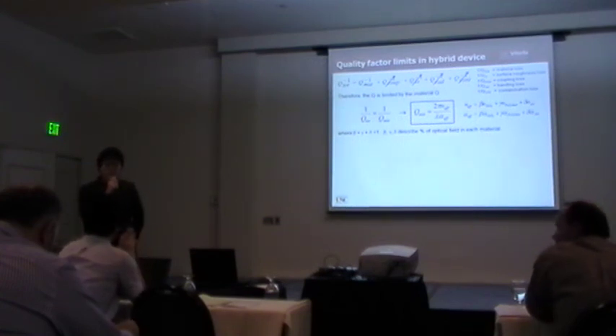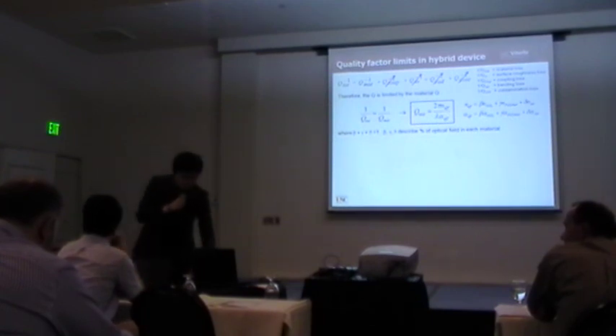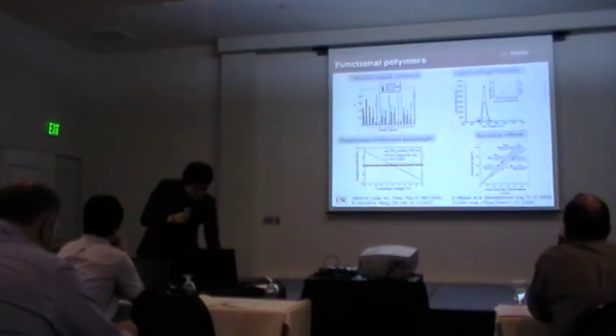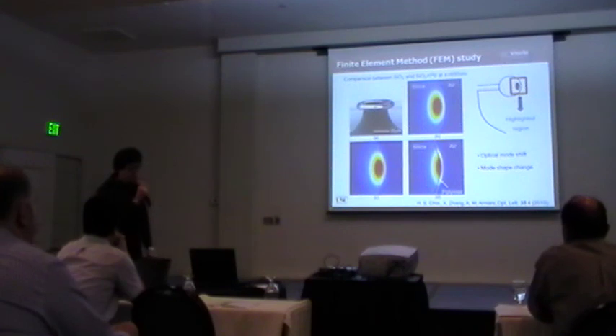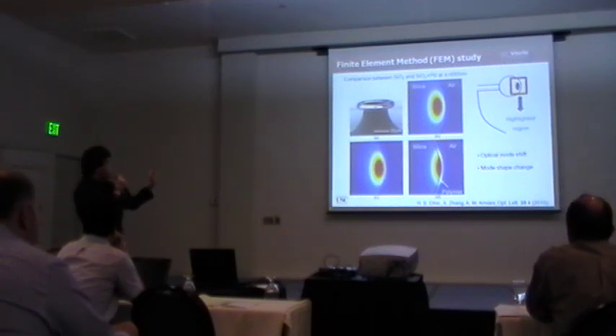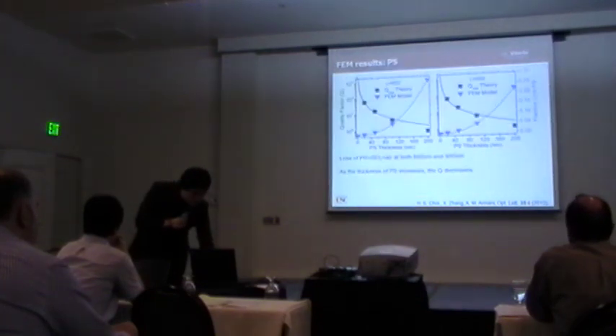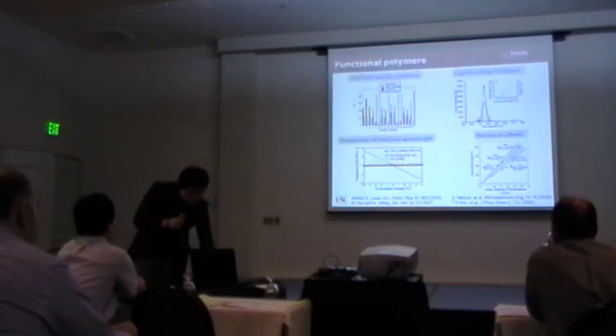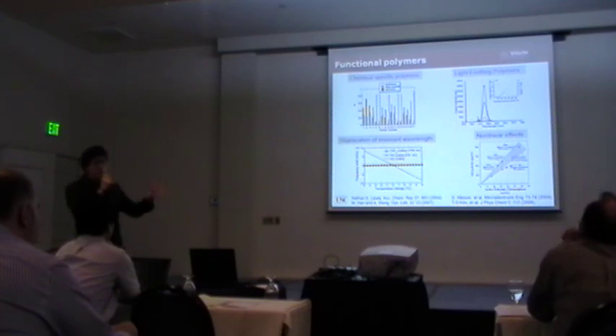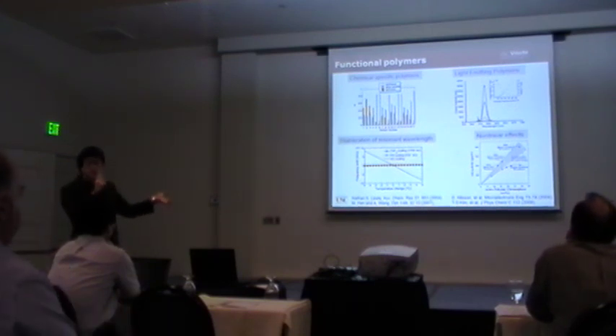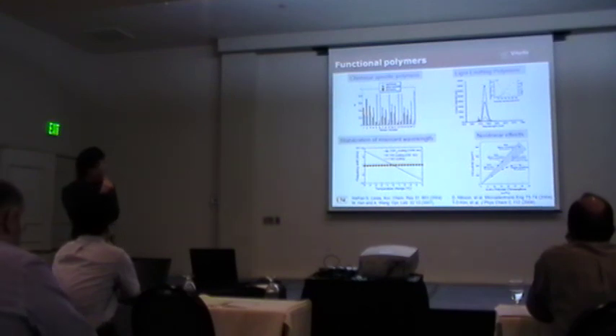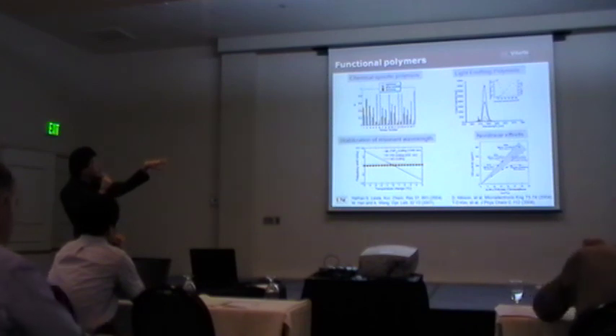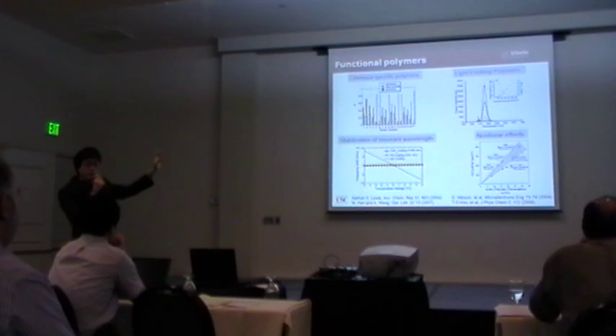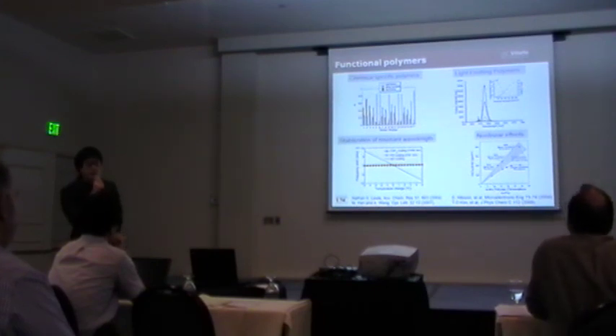What is the effect of using a polymer that decreases the Q factor? Even though it decreases the Q factor, one advantage is we can move the optical field strongly into the polymer layer. By moving a strong optical field into the polymer layer, we can study polymers on silica microtoroids and make a strong interaction of the field in the polymer layer. For example, if we use light-emitting polymers, we can make a strong interaction in the polymer layer and maybe make low loss lasers, something like that.